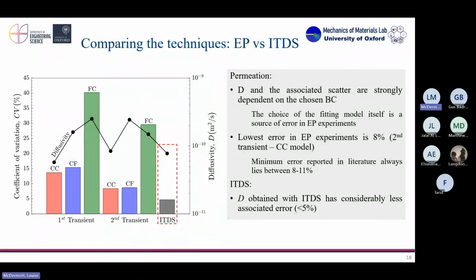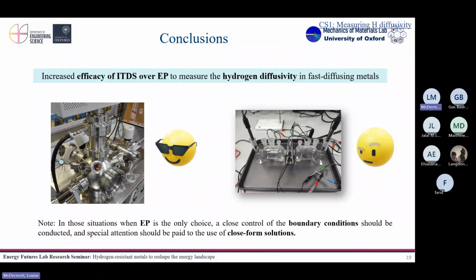And if I compare it with isothermal TDS, I'm getting almost the same result. Also, you have to consider the orders of magnitude we are working with in diffusivity, something of the order of 10^-10. With isothermal TDS, we obtain the same value as permeation, but the error was considerably lower. It was below 5% in more than 10 measurements, while in permeation, the lowest we could obtain was around 8%, and I had to assume things. In TDS, I know exactly my boundary conditions because I have hydrogen in the sample, and outside I have vacuum. So that's clear.